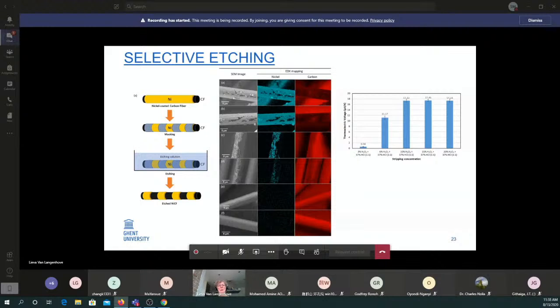Selective etching, here you can see some results. We had to elaborate a method for the etching because there was no literature. And here you can see how by increasing the concentration of peroxide, how the nickel is disappearing and how the carbon layer, the carbon core becomes visible.